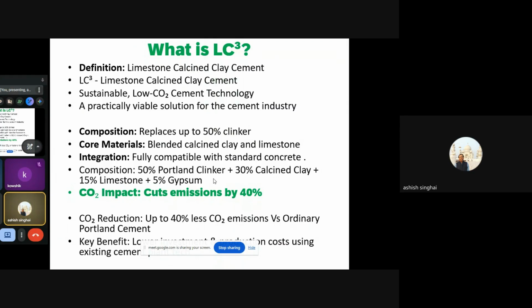50% is clinker, 30% is calcined clay, and 15% is limestone, plus 5% gypsum added as a set retarder. Okay, this is the composition. Carbon dioxide impact is cut down by 40%. This is the beauty of LC3, which is why it is being considered as one of the most sustainable cements, or in other words, a kind of green cement by the global construction industry.